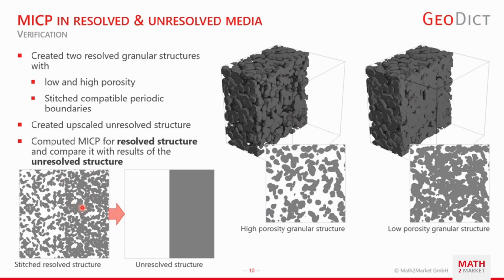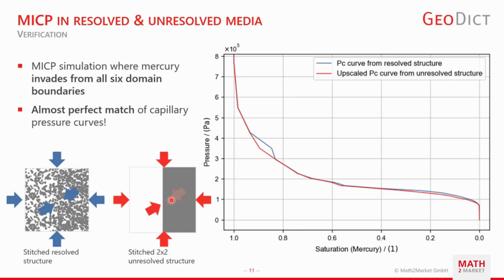Because we have only resolved structure capillary pressure curves and only non-resolved structures. And as you can see, the match is quite good. So for the resolved structure, or the blue curve, we have an almost identical curve as for the upscaled curve. Only here, at that narrow part of saturation above 90% or around 90%, we have a small deviation that could also be a boundary effect of this structure here.